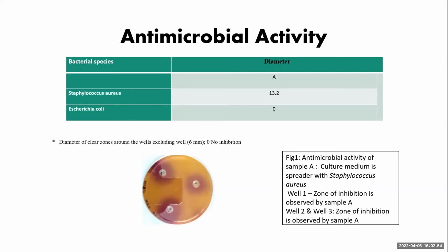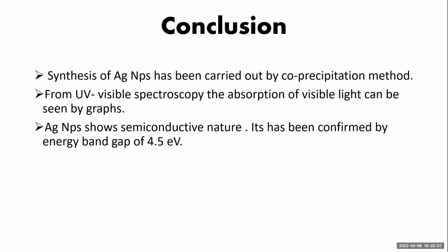Now the conclusion: synthesis of Ag nanoparticles has been carried out by the co-precipitation method. From UV-visible spectroscopy, the absorption of visible light can be seen in the graphs. Ag nanoparticles show semiconductive nature. It has been confirmed by the energy band gap of 4.5 electron volts.